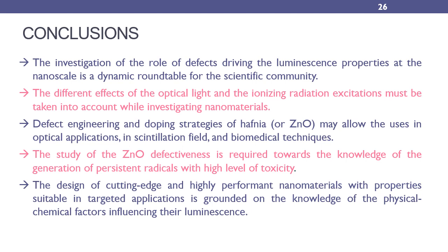For my presentation, I have chosen hafnium oxide and zinc oxide as representative nanomaterials due to their outstanding qualities. The focus of my presentation has been the description of the different factors that enable to govern the luminescence properties of nanomaterials. From the choice of the synthesis, the use of doping strategy to the annealing treatments, all these procedures allow to control the nanomaterial size as well as the type and the concentration of defects that can either switch on or quench the luminescence as demonstrated for the case of hafnium, or also they can affect the surface chemical reactivity as in zinc oxide nanoparticles.